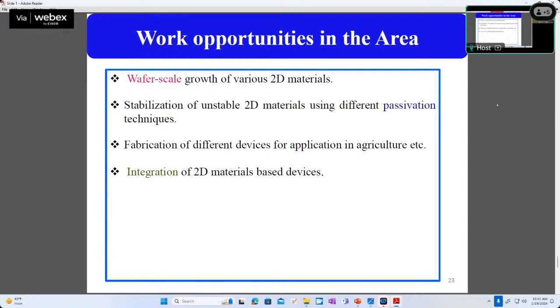Another thing is a few of these family members are unstable in atmosphere, so one can work on the stability part. Different passivating materials one can check for whether they are suitable or not, because if you vary the passivating material, the film below it is under stress. Okay, so which one is suitable, one has to identify. So one area can be stabilizing the 2D material films using passivation techniques.